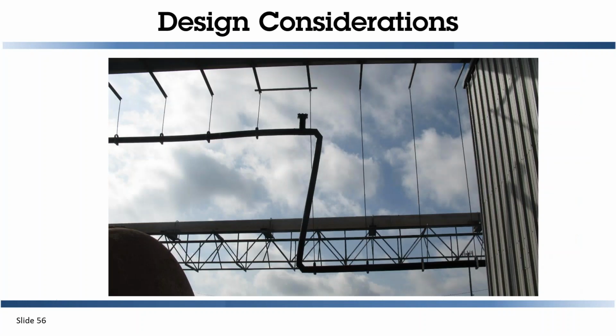Here's a good example of an expansion loop using a change in direction. This is outside of a building, and obviously ambient temperature changes. This Z shape will actually move counter to itself, and so the bending does not put extra stress on the pipe because the riser height is long enough.